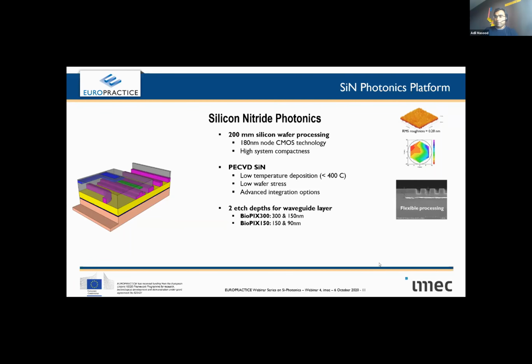With silicon nitride, the problem is, or it's not a problem with silicon nitride, but the applications in visible light really span a very long spectrum, as I showed in a previous slide. So starting from, let's say, 400 nanometers of wavelength going up to way larger. It can even cross the mid-IR range and all. So what thickness of silicon nitride should be standardized? And the answer is nothing, in my opinion, because if the applications are so varied, it's very difficult to fix one thickness where eventually all foundries start making similar kinds of devices.